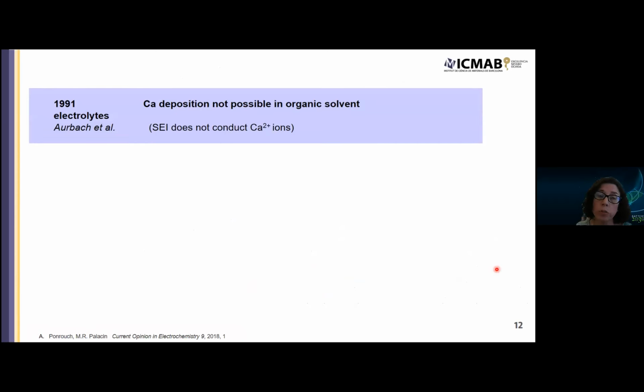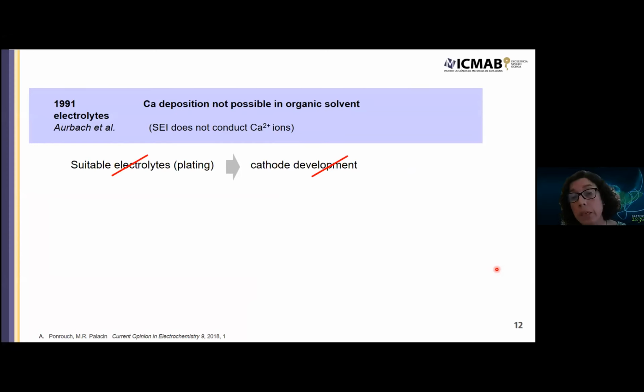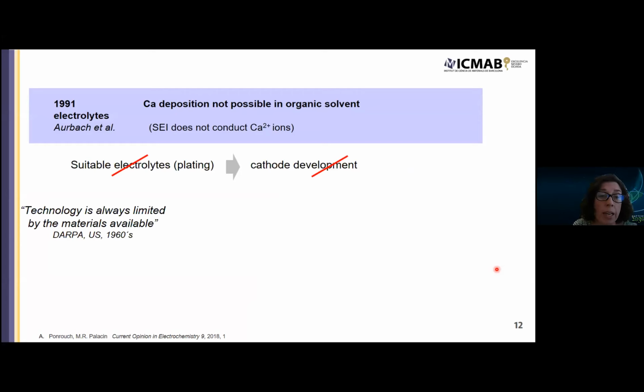And after the papers I mentioned to you, there was a seminal work by the group of Doron Aurbach, who attempted again calcium deposition in organic solvents, pretty much like those used for the lithium-ion technology. And they concluded that it was not possible. And again, the reason seemed to be that the SEI did not enable transport of calcium ions. And of course, if there are no suitable electrolytes for plating, this hindered a lot the development of cathodes, despite intercalation of calcium in some compounds being tested, but it was really scattered studies. And as this DARPA adage in the US said in the 60s, technology is always limited by the materials available.